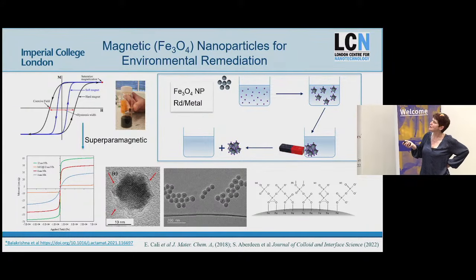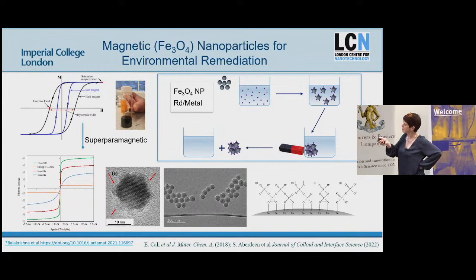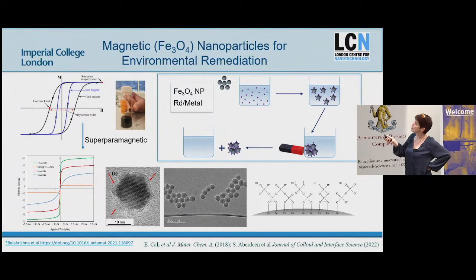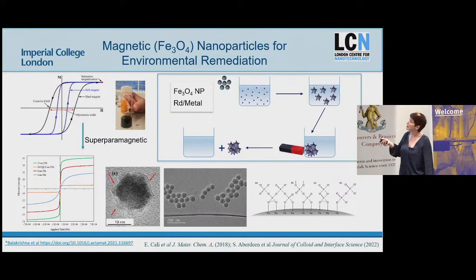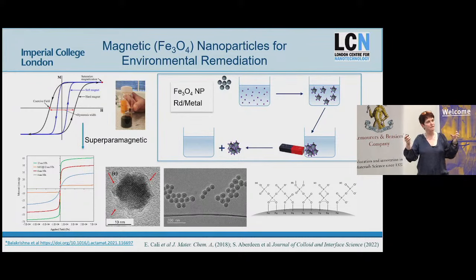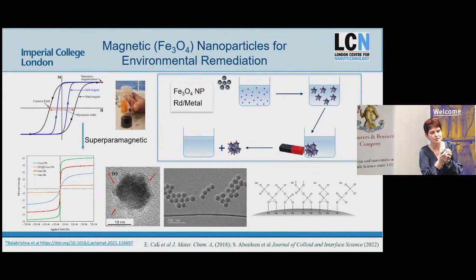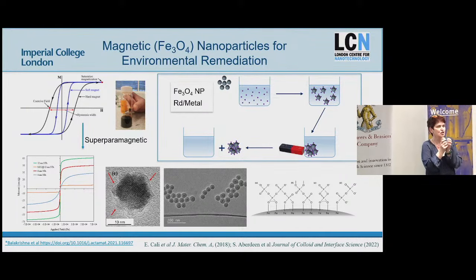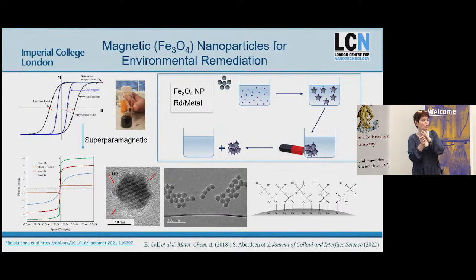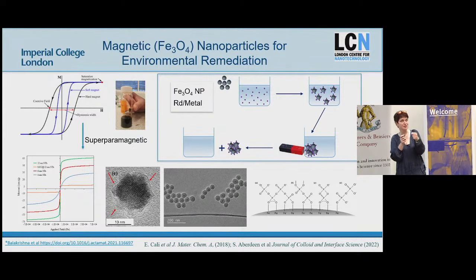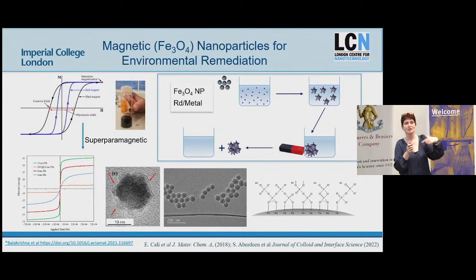So this is a hysteresis loop for a conventional ferrimagnetic material. You apply a field, you get a saturation magnetization, you reverse the field, and even at zero field, you maintain the magnetization, right? And you have to put an extra negative field on to demagnetize the system. When you make your material very, very small, and you contain all your magnetic atoms and electrons in a small volume, it does not sustain that magnetization when you remove the field, because the volume is so small that just thermal fluctuations will demagnetize it.